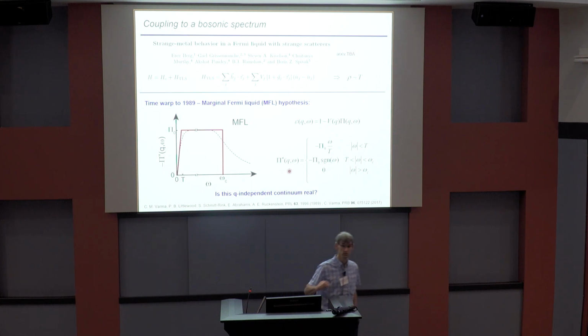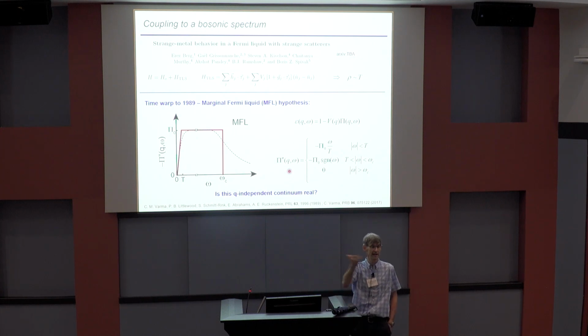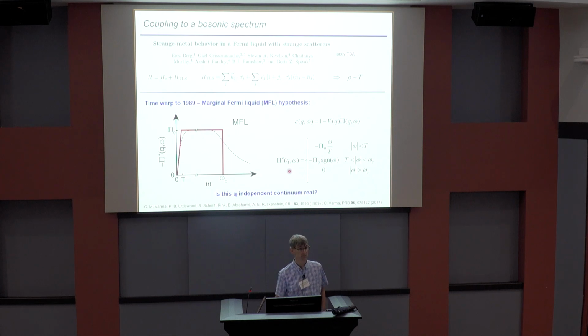So the way you kill quasi-particles everywhere on the Fermi surface by invoking a continuum is that the continuum needs to be present at all momenta. Because if it's some kind of dispersing excitation like you'd get in a Fermi liquid, then it's not going to act everywhere on the Fermi surface uniformly. So this is an experimental question. Does this Q-independent continuum exist? And if it does, can it explain the bizarre properties of strange metals?